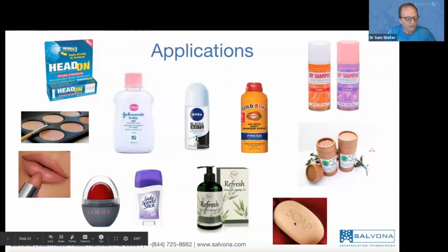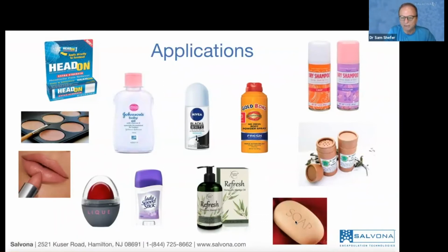Bar cannot handle liquid ingredients and cannot handle acid. Our major business for Estée Lauder is encapsulating salicylic acid. Why is it not compatible? Because the bar is base, alkaline, and you cannot incorporate acid and base without a reaction. By isolating the acid, encapsulating it, now we can incorporate it into the soap and it's stable. And then when you wash, the water will activate and release the salicylic acid.